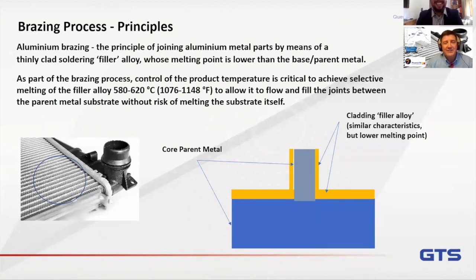But yes, the challenge you quite rightly allude to, Victor, is the fact that we're selectively melting the filler metal with the aluminium. So what we don't want to do is take the temperature of the filler metal too close to the temperature that the aluminium substrate, or the parent material, could potentially melt. And that temperature window is quite tight in aluminium brazing, because typically the filler alloy is going to be melting between 580 to 620 degrees. And as we all know, aluminium will melt at around 650 to 655 degrees Celsius.